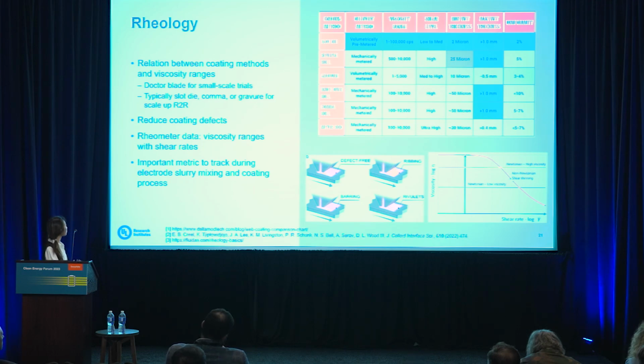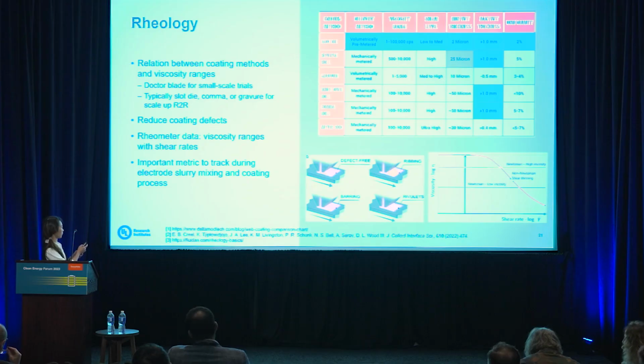For the rheometer, the data that it provides is viscosity against shear rate. It's a really important metric to track during the slurry mixing and coating process. I'm sure everyone has some experience where, if you change your recipe or change an active material, your slurry doesn't come out the way that you want it. So it's a very important metric to track, and you need to do some rheology measurements every time you change your slurry mixing process.